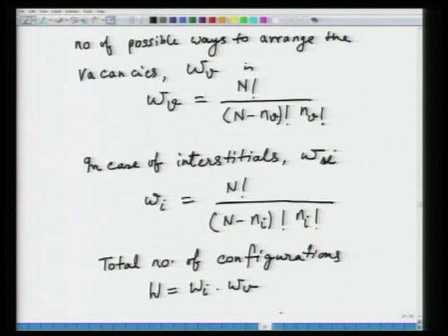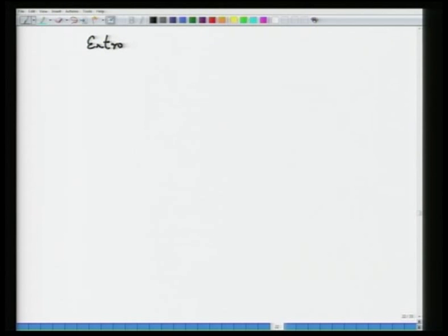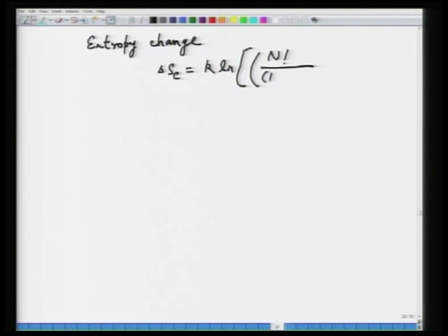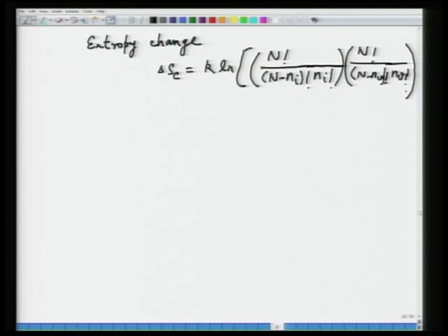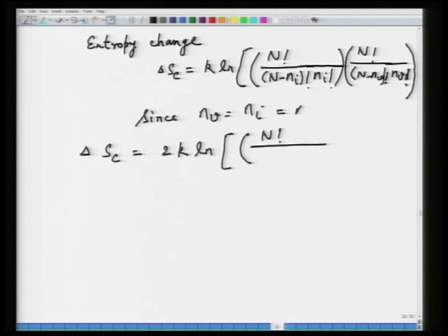So, as a result we can work out what the entropy change is. The entropy change, delta Sc, is equal to k ln of N factorial divided by (N minus Ni) factorial into Ni factorial, and again (N minus Nv) factorial into Nv factorial. Now, since we know that Nv is equal to Ni, we can write this as 2k ln of N factorial divided by (N minus n) factorial into n factorial.